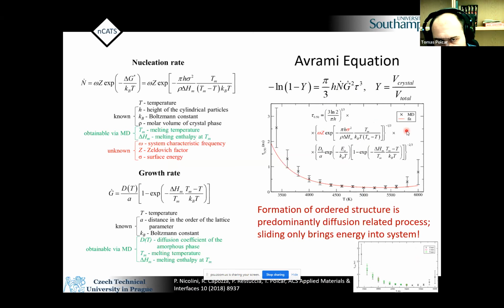And he used basically the traditional Avrami equation, which shows the progress of crystallization, where this Y is the ratio of the volume of crystalline phase divided by the total volume. So for fully amorphous, of course, you will get zero. For fully crystalline, you will get one. And this Avrami equation uses basically two key parameters, the nucleation rate and the growth rate, and time, of course. For the nucleation rate, we can calculate it, but we don't have all parameters. Some of them we can obtain via molecular dynamics directly, like melting temperature or melting enthalpy. Some of them we don't know and we cannot get. And then there is the growth rate, and again, we can obtain everything we need from molecular dynamics. So what we can do is take this equation and do fitting to get these three parameters. And that's what we got.